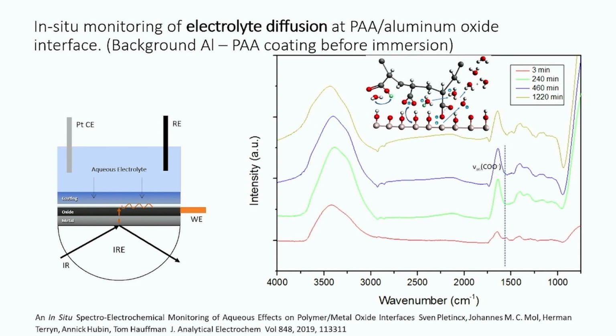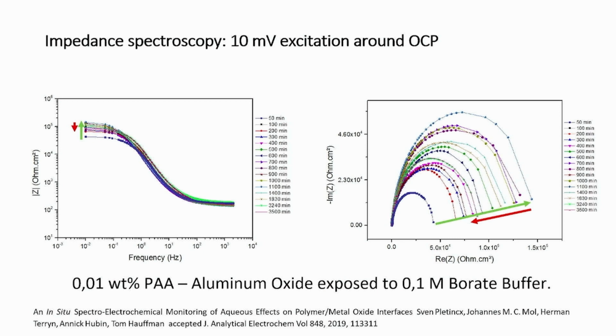If you now combine that with the impedance measurements, just remember these impedance measurements are done in the same time domain as the infrared measurements, and the high frequencies and the low frequencies are measured in the same time domain. We can actually follow the bond by the impedance measurements, because we have the infrared signal and we have the impedance measurements. This allows us now to use the impedance measurement as a monitoring system of the interfacial properties.